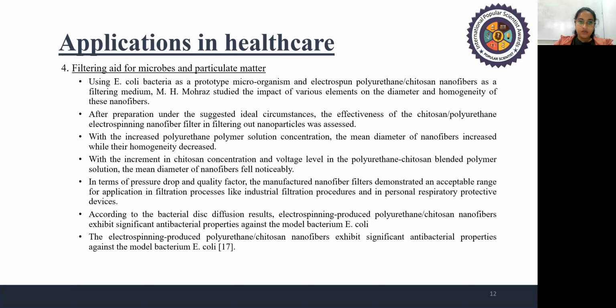And therefore, according to the bacterial disk diffusion result, the electrospun polyurethane chitosan nanofiber exhibits significant antibacterial properties against the model bacterium E. coli.